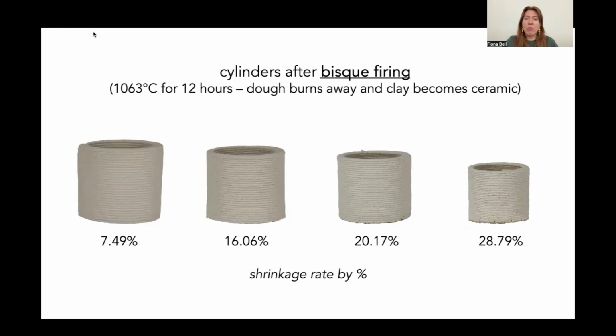Once the cylinders reached a bone-dry state, they were bisque fired in a kiln. Bisque firing occurs at a relatively low firing temperature. During this firing stage, the dough burns away and the clay chemically transitions into a ceramic. This causes much more dramatic shrinking to occur.